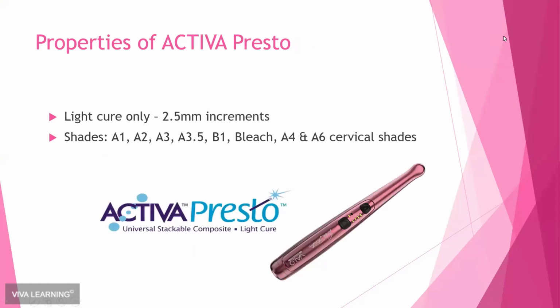When we're looking at the Activa Presto, I have my curing light here to remind you that it is light cure only, and you're going to cure that in 2.5 millimeter increments. So this is going to be treated more like a conventional composite in that sense, as far as you're not going to be able to bulk fill this material. You're going to want to pay attention to the depth at which you're placing it.